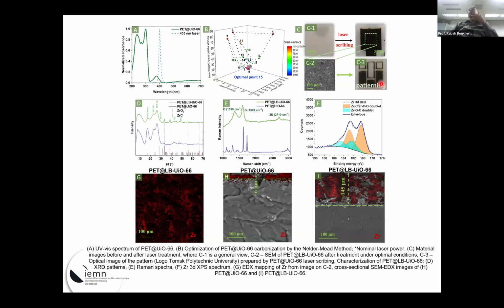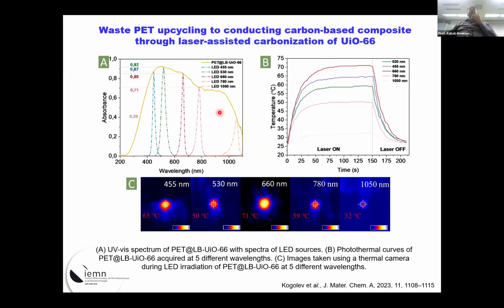You can see as well we can pattern because it's a laser. Initially, when you have the MOF, you see the thickness is about 6 micron. But after laser writing, we have about 145 micrometer. And here at the bottom it's the plastic. Interestingly, this material, when you shine light on it, generates heat. So we can definitely use it for photothermal applications. We have a lot of interest in photothermal materials for biomedical application, for delivering drugs, but also for killing bacteria, especially for anything that is on the surface. We can definitely heat up sufficiently to treat, for example, wound healing or a cancer which is on the surface.